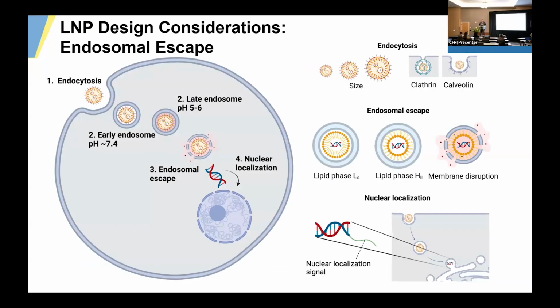So when you put all that together, the art of what we're trying to do is this: these types of nanoparticles enter into the cell by a process called endocytosis. And as the particles are endocytosed into the cell, they are carried by a structure called an endosome. And as that endosome travels to a lysosome, which is kind of like the garbage disposal of your cells, there's essentially a pH change whereby that ionizable lipid kicks out the cargo and dumps it into the cytoplasm. And so the trick is to design the particles so you have that effect and release the cargo before everything gets to the garbage disposal.